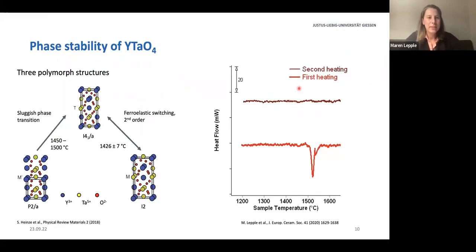So concerning the phase stability of the yttria tantalate phase, there were some uncertainties in the literature. So three different structures were reported in the literature. At room temperature, two monoclinic phases were reported to be stable. One was the M' phase and one was the M phase. And at high temperatures, the tetragonal phase is stable.